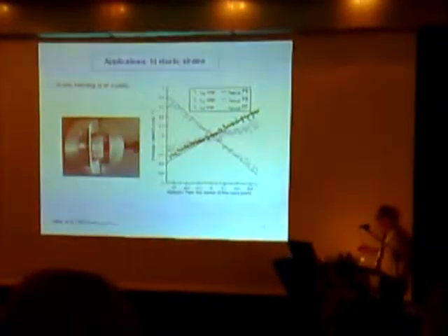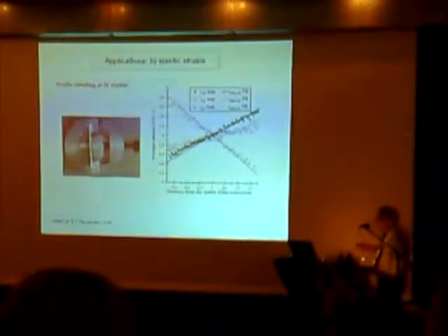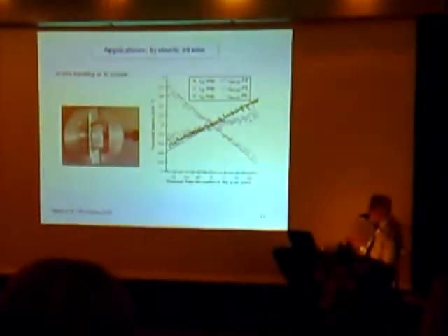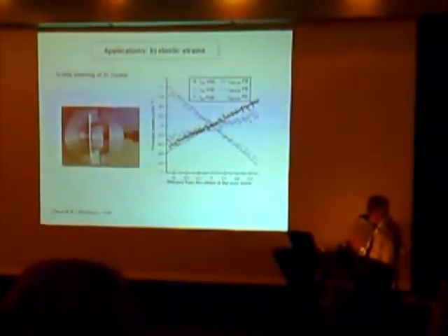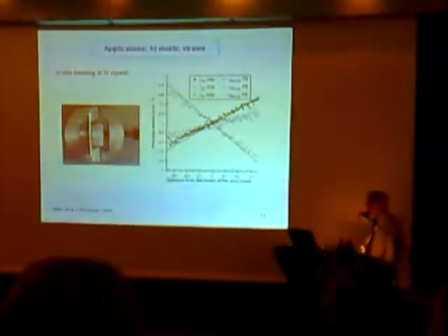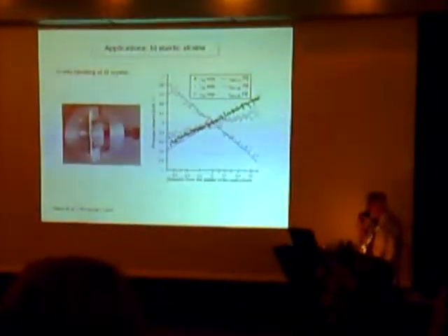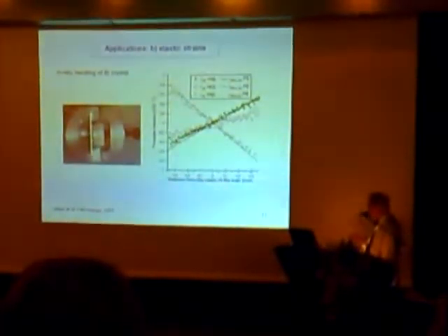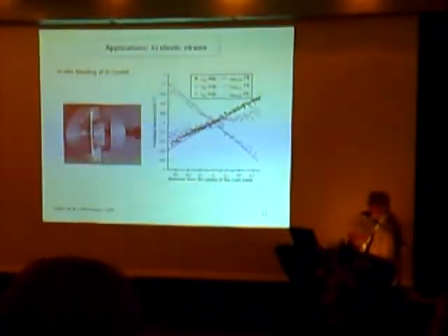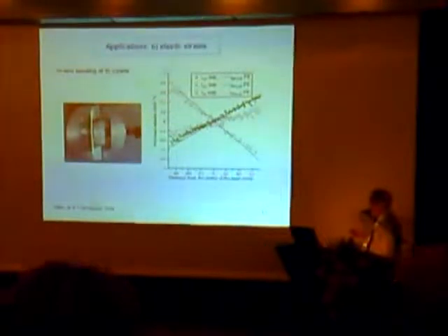Second is looking at just pure elastic strains without any plastic deformation for the moment. And this is work that was done by Willett a few years ago. He took a silicon single crystal and bent it, four-point bending in a microscope. Now, of course, when you bend a crystal, one surface is in compression, the other surface is in tension, and the center is zero, so you have a reference which is right in the middle. Then using this technique, you can scan it. What he did at the time, in fact, was a stage scan, because we knew that beam scans at the time were dangerous. At the time, we didn't have the correction for the beam scan, but we did the stage scan, so we went through here, this is distance, and measured the strains. And these are different strains, Y, X, Z, and all the rest of them.